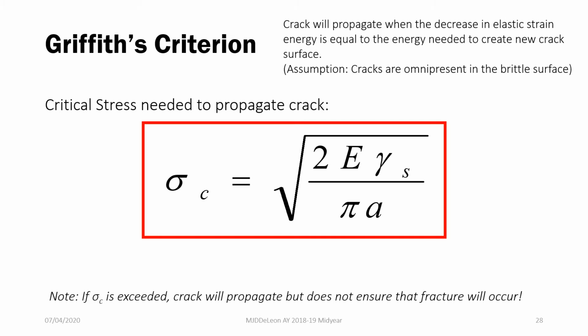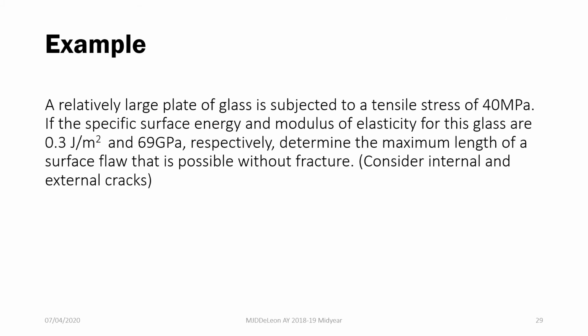But this does not ensure that your fracture would occur, because you also need to learn whether or not your material is ductile or brittle. So now let's look at an example for Griffith's criterion. A relatively large plate of glass is subjected to a tensile stress of 40 megapascals. If the specific surface energy and modulus of elasticity for this glass are 0.3 joules per meter squared and 69 gigapascals respectively, let's determine the maximum length of a surface flaw that is possible without fracture. So in this case, we're determining the length of our crack in the surface.